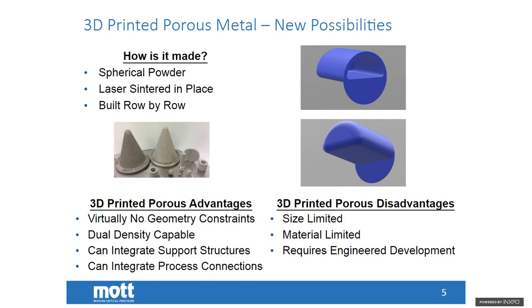There are disadvantages, of course. Porous metal sintering machines have a limited size — they can only print approximately 12 inches by 12 inches, varying by manufacturer. Material is limited by what's been developed and the ability to sinter. Additionally, 3D printing requires engineering models and tooling to get the printer up and running, whereas a porous metal disc can be produced on an axial hydraulic press by the thousands or millions.